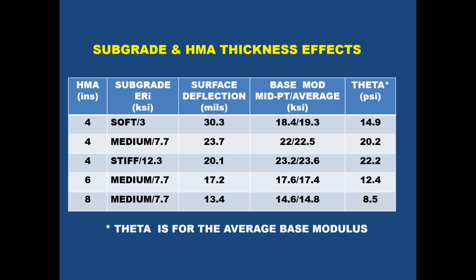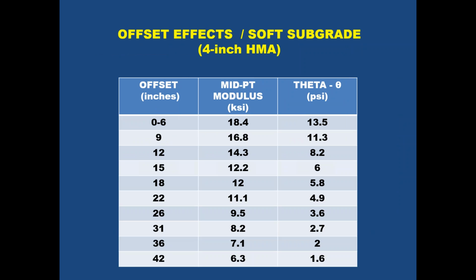Okay, what happens as you move horizontally from, quote, the loaded area? Stresses do what? Go up or go down in the granular material and the subgrade? Go down. Okay. If you look at the value of theta we get, that's basically under the load plate, okay? Then we're at 9-inch offset, 12 inches, etc. Look at these values you get for theta when you get out there at those points remote from the loaded area. You've got modulus values that are insignificant almost, right? In fact, they may be lower than the subgrade.